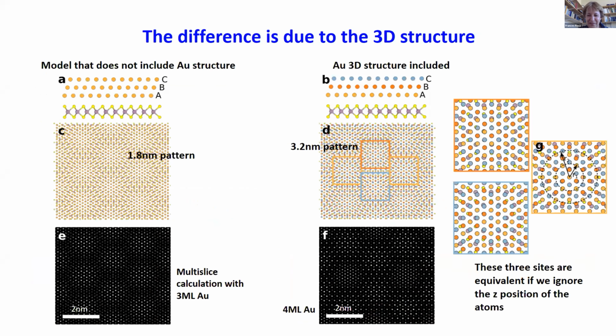And again, we stared at it for a very long time and then worked out that the reason the two periods are different is because TEM is giving you a projection image. When you look through the sample, you're looking at the 3 layers of gold atoms within the gold crystal, the ABC stacking of the gold lattice structure. And if you don't care what height they're at, and you project this pattern on top of the MoS2 pattern, you get a moiré that looks like this with a 1.8 nanometer repeat distance.